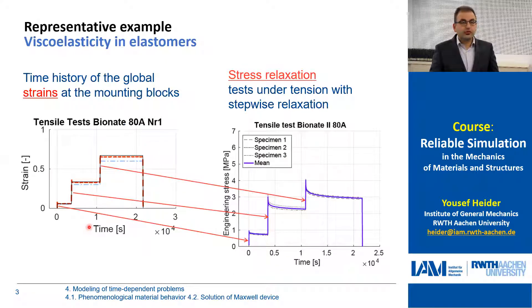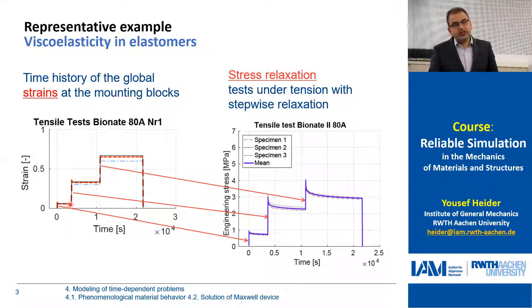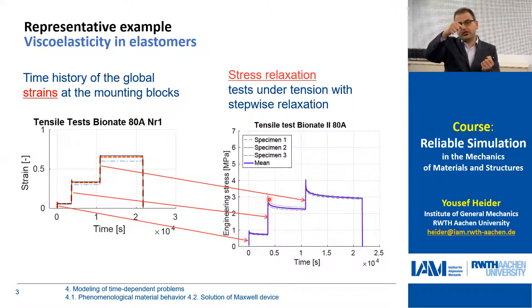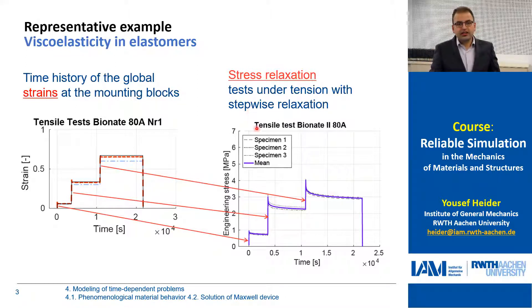We applied stepwise displacements so the strains can be computed thereafter. We apply the displacement and wait a little bit, because time-dependent behavior means the behavior changes over time. We see the strain applied and then look at the corresponding stress. The stress increases, and then if we wait — we fix our hands and measure the force — by time the force gets lower, so it relaxes. The stress decreases until it reaches a stable value after a long time.